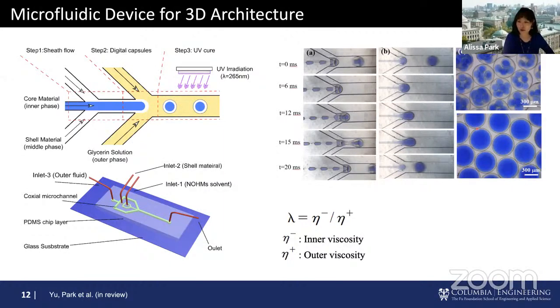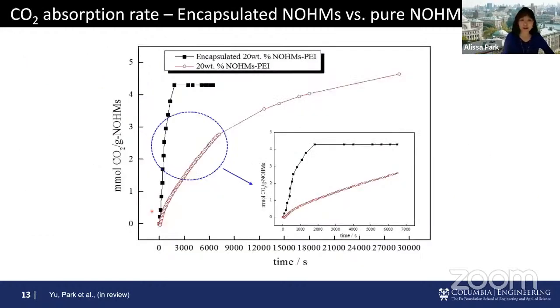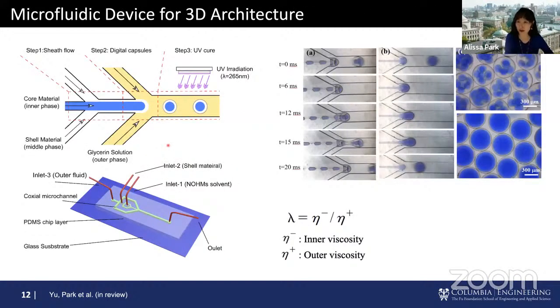And by tuning the thickness of these gas permeable kind of membrane-like shell, we were able to let CO2 in very quickly. So as we expected, compared to neat NOHMs, we really increased the CO2 capture capacity, kinetics of CO2 capture tremendously. But going back to here, you can imagine that single core versus the multi-core will have a lot more interfacial area, and it will enhance the rate of CO2 capture even faster.